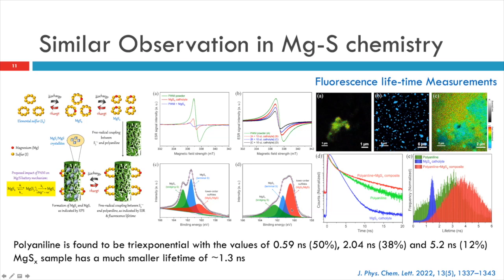But when you do polyaniline together with magnesium sulfide, we see that the lifetime is increasing. You see the red plot, the distribution is a little bit spread out. So we need to do more control experiments. Here we were supposed to do it in situ. We have not done it because of limitations of the experimentation, so in the near future we'll be doing that.